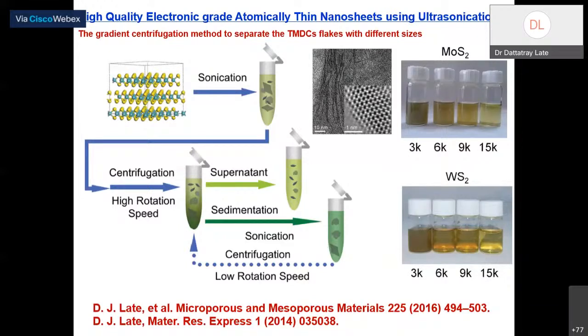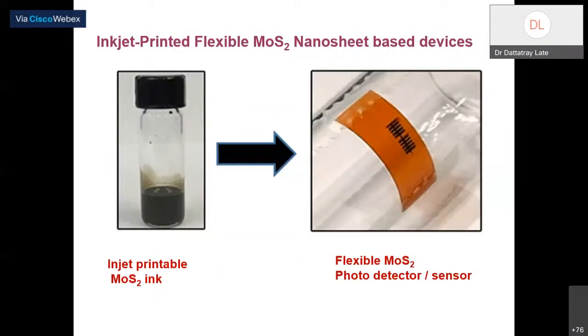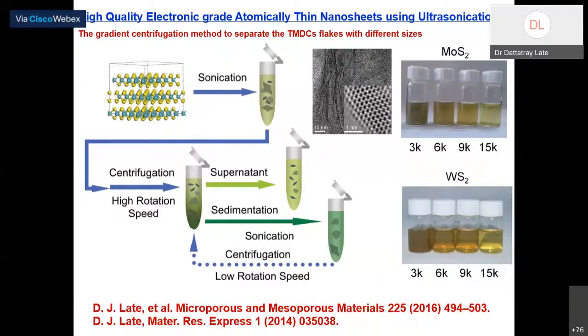Why am I getting different color contrast? Because the thickness of layers is different at 3000, 6000, 9000, and 15,000, right? So this also gives you thickness-dependent properties of this ultrasonicated atomically thin MoS2 and MoS2-like other materials, like WS2, MoSe2, WSe2, SnS2, and all these things.